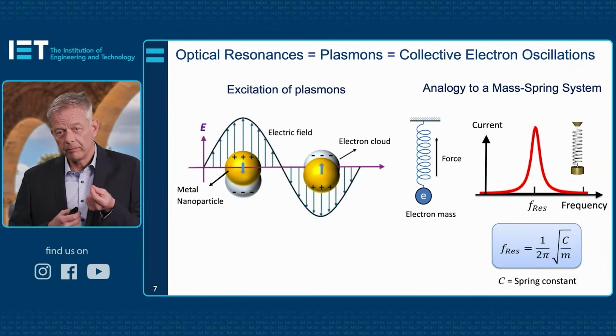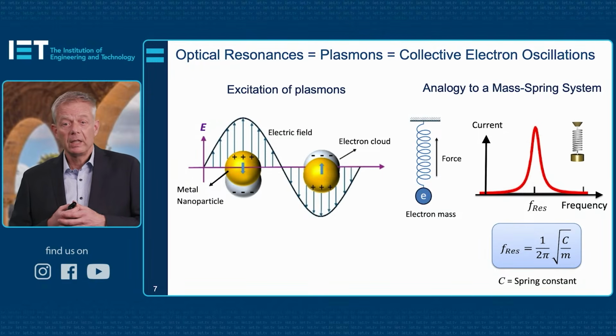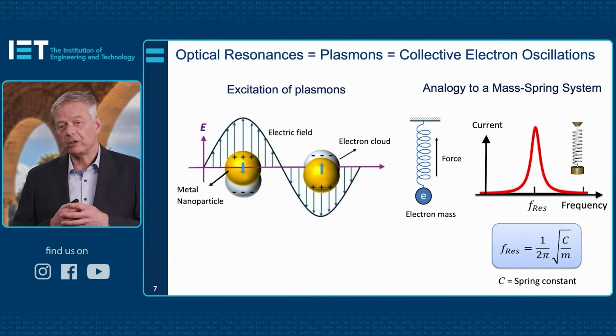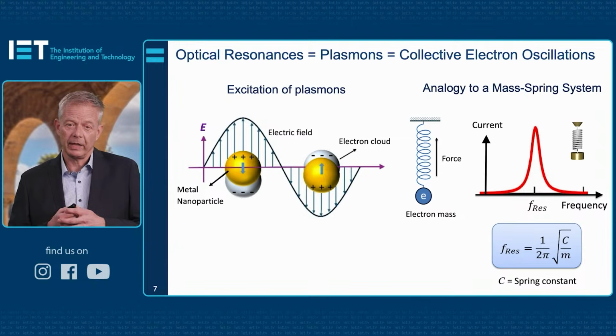This current can cause, like in a metallic wire, absorption and heat if I run high currents through a metal wire, or also scattering by this metallic particle. So at this resonance frequency, I can very efficiently convert light energy to motion of electrons to then heat dissipation or light scattering subsequently. Now this resonance frequency, we can mathematically derive, is related to the spring constant C divided by the mass of the electron and the square root of that.